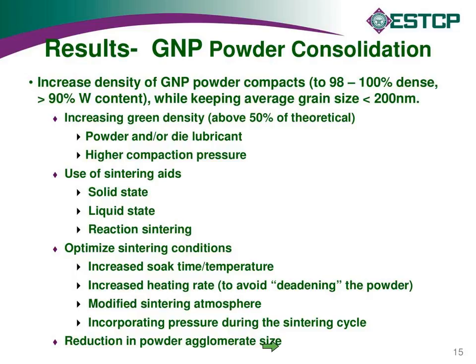So there's a pretty well-known challenge in consolidating these nanostructured materials and maintaining the nanostructure. There's some basic physics that occurs with the contact angles of the particulate during sintering operations that ultimately limit what you can do. So in a lot of cases, you're required to use extremely high compaction pressures to facilitate compaction of the powder prior to sintering it. And then what we tried to do with sintering aids is, since sintering is controlled by surface diffusion between the particulate, we tried to add small amounts of elemental constituents to facilitate the diffusion without causing grain growth. One of the best actors for that is nickel. So in some cases we used small additions of nickel to enhance the diffusion of the tungsten.